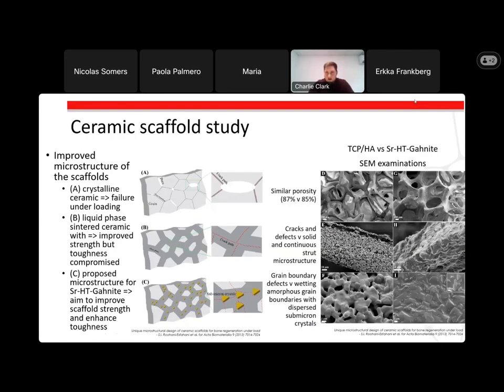When we look at the SEM examinations comparing the TCP with the new material, you see there's very similar porosity afterwards. You can see the cracks and the defects in the TCP, but with the new material there's a solid continuous microstructure all throughout. And we can see that in the TCP and HAP there are some grain boundary defects, whereas when you look at the new material, there are very well-wetting amorphous grain boundaries, and you can just about see the dispersed sub-micron crystals that help to deflect the path of the cracks.